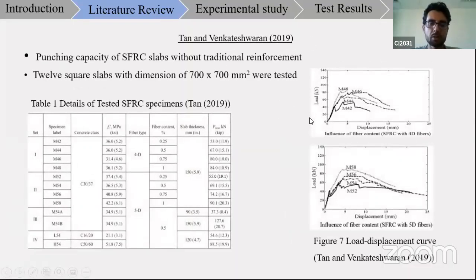The second literature review I will present is Tan and Venkateshwaran. In this study, the punching capacity of steel fiber reinforced concrete slabs without traditional reinforcement was investigated. And they tested 12 square slabs with dimensions of 700 by 700 millimeters. And the concrete class is shown here, and 2 types of fibers were used. And the fiber content ranged from 0.25 to 1%. As shown in the load displacement curve, the type of fibers had marginal influence on the failure load.